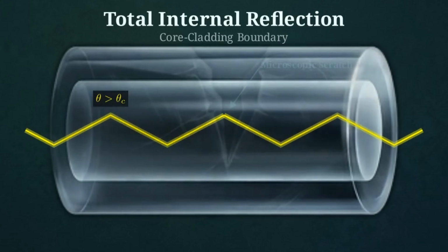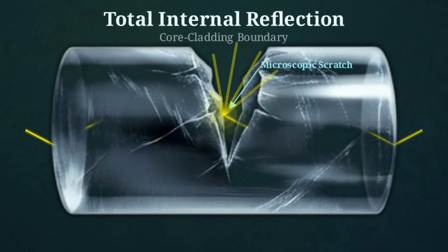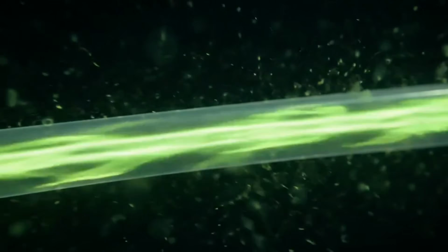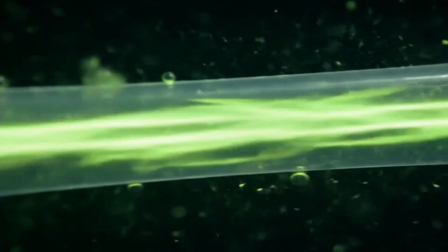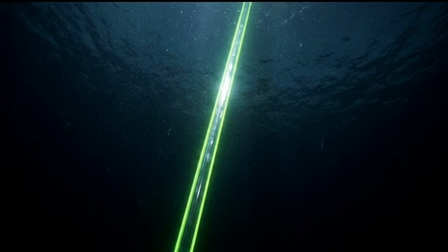If the surface has even a microscopic nick or scratch, the reflection barrier is compromised. The light leaks out sideways into the surrounding darkness. The result is a failure of camouflage. The line suddenly flashes with a harsh neon glow. The same chemical engineering used to hide the line has turned it into a fiber-optic beacon.